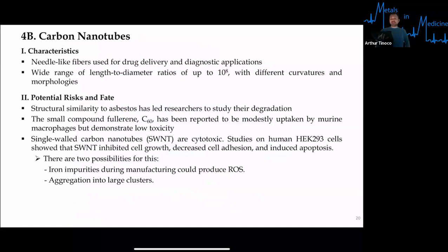They are structurally similar to asbestos, and so for this reason, researchers have extensively looked into the study of their degradation. So the small compound fullerene, C60, has been reported to be modestly uptaken by murine macrophages, but demonstrates low toxicity. However, single-walled carbon nanotubes, abbreviated SWNT, are quite cytotoxic. So you have a number of studies, for instance, with the human HEK-293 cells. Those are classically used as an assessment of the general toxicity of different materials. They show that these nanotubes can inhibit cell growth, can decrease cell adhesion, and can induce apoptosis.